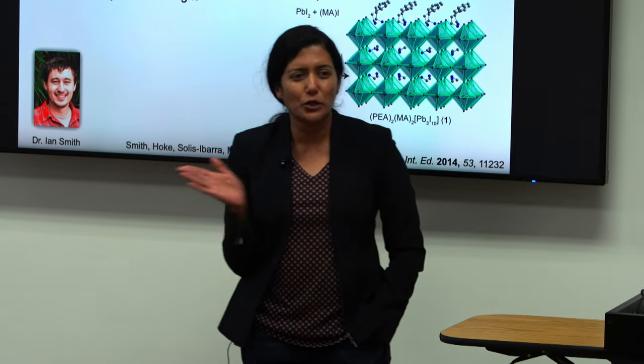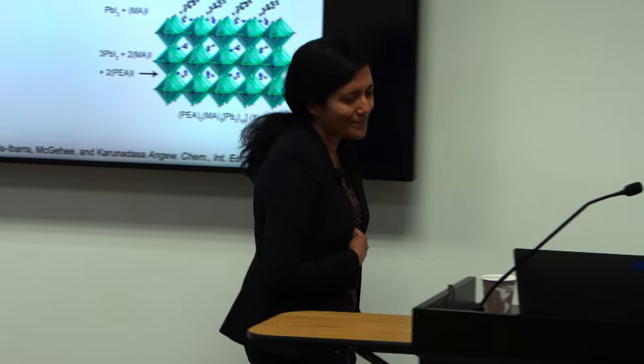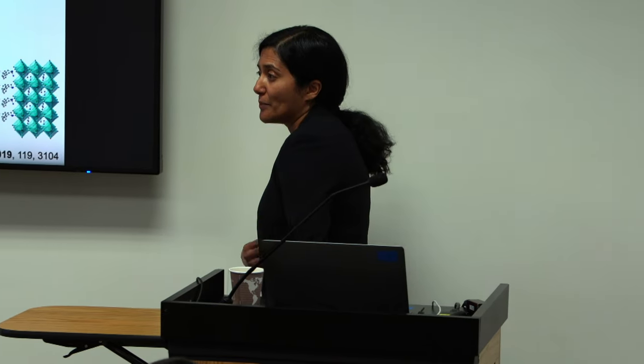So we asked the question, how do we engineer moisture resistance into the material as an intrinsic part of the material? So we were very excited to show the first example of a 2D perovskite solar cell. The idea here is that we can make materials that look like this 3D perovskite has been sliced by this really tiny knife that can cut three-layer thick slices of my 3D material. And we can put organic molecules between these layers, and these organic molecules are a lot more hydrophobic than the perovskite. So it's almost like we've taken the 3D material, sliced it very finely, and coated it with a waterproof coating. So these materials turned out to be much more resistant to moisture, and in fact, we could make solar cells out in air. And to date, device engineers are making really high efficiency devices out in air by using a mixture of 2D and 3D perovskites.